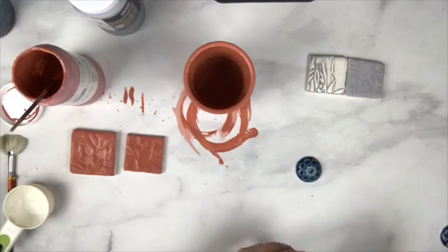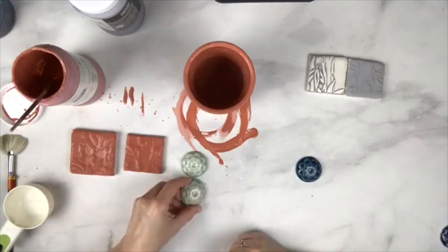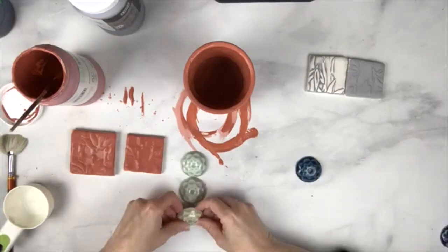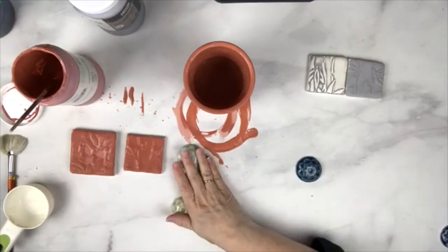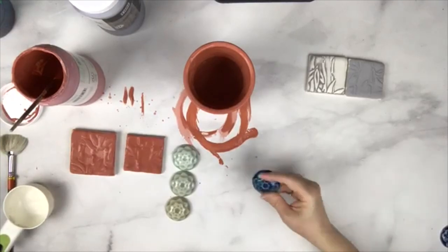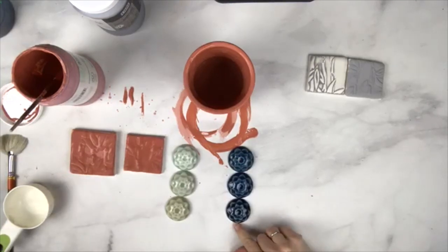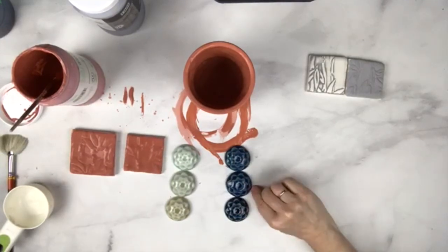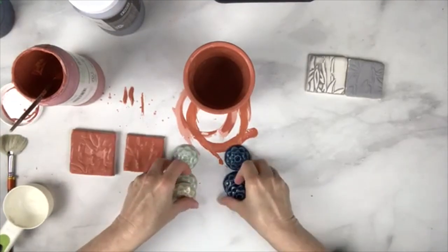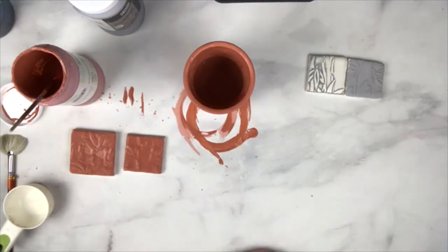Most of the colors come out the same. The last one I'll show you that does not is aqua — looks great at cone six, starts to shift a little greenish at cone seven, and at cone ten is totally green. However, most of the colors don't really change much. For example, this is C29, deep sea — that's at cone six, that's at cone seven, and that's at cone ten. It just becomes a really rich, almost cobalt blue, and loses some of the warmer tones.